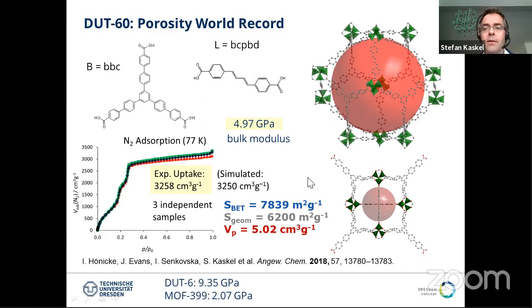One important point is, of course, that the mechanical stability of these very thin and fragile networks becomes weaker and weaker. And therefore, it is very challenging to maintain the porosity in these types of networks. So we calculated, and this is the strength of theory and in silico design, in this case done by Jack Evans, a bulk modulus of 4-5 gigapascal for this material, meaning the strength of the material. And just to get an idea, DUT-6 has already 9 gigapascal, so a factor of 2 higher, and is quite rigid. So this becomes softer and softer.